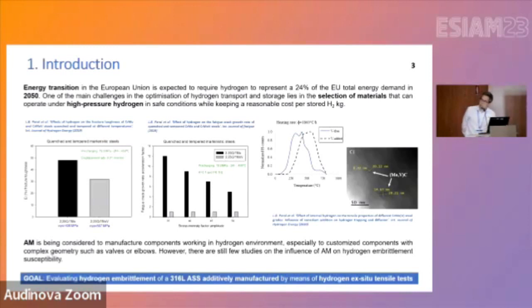During the last years, we have characterized the influence of hydrogen in quench and tempered martensitic steel, revealing the important influence of the nanometric vanadium carbides precipitated during the tempering treatments. So this type of strong traps plays an important role in the embrittlement process in order to alleviate hydrogen susceptibility, even increasing the yield strength without increasing the hydrogen embrittlement susceptibility.